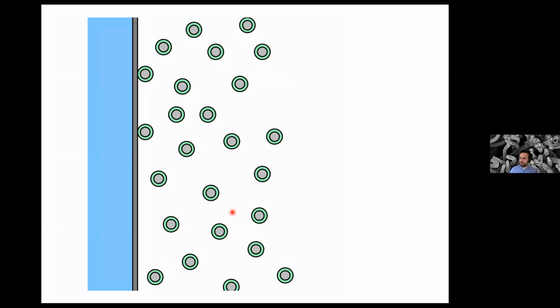So on the cathode, what we have is typically a membrane, then a catalytic layer here, and then we have these gas diffusion layers or gas diffusion electrodes that I'm sure you're all familiar with, which are composed typically of carbon fibers and then a hydrophobic coating, typically PTFE, Teflon, yeah? And the reason why you put in a hydrophobic coating is that the water or the products can come out as quickly as possible.